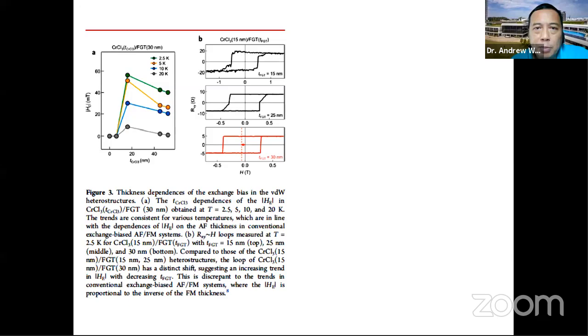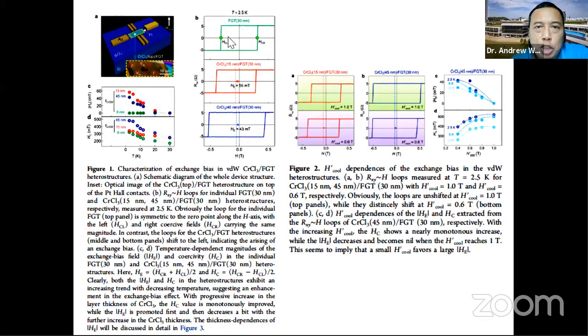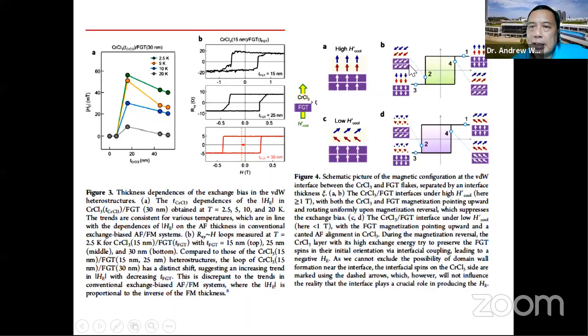Just moving back to the previous one, if you work on just FGT, it's symmetric. You don't see this exchange bias. So only when you put this antiferromagnetic CrCl3 at the right thickness, you can see this exchange bias. So without going to details, this is a pictorial explanation of this exchange bias effect. It shows the pinning of the spins in this bottom case where the ferromagnet can't quite flip, and that results in the shifting of the hysteresis loop.